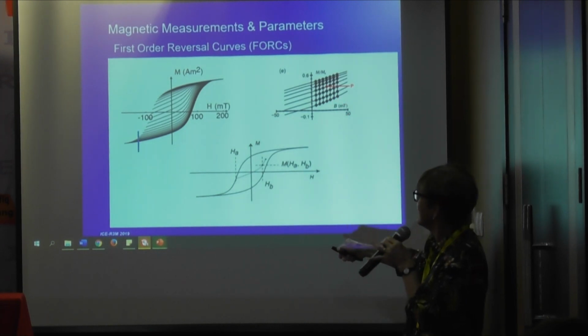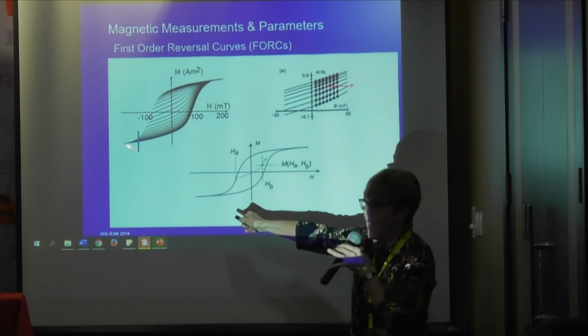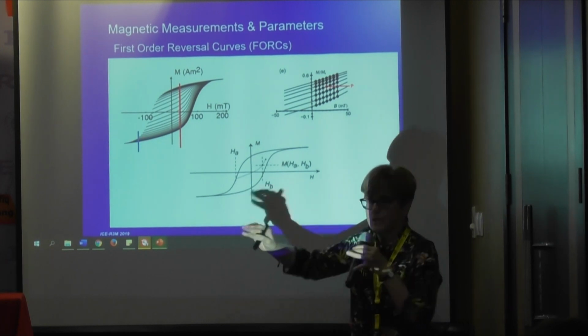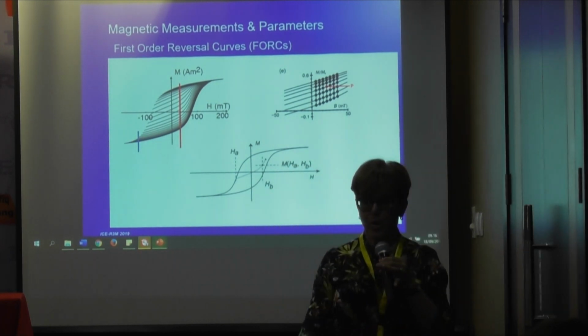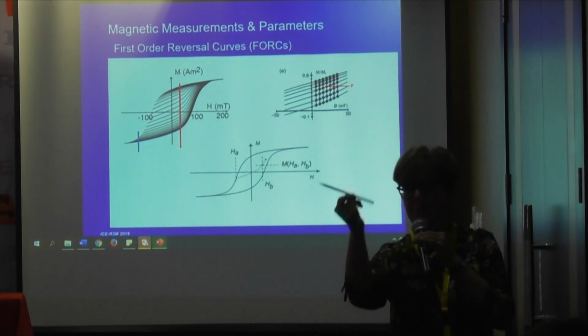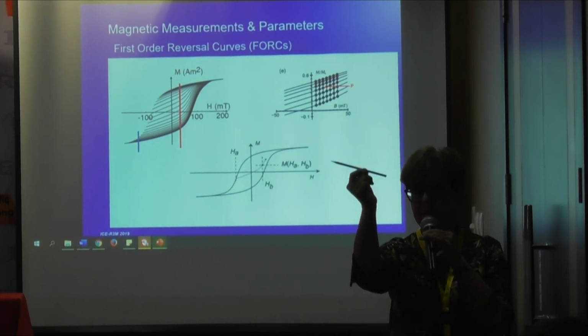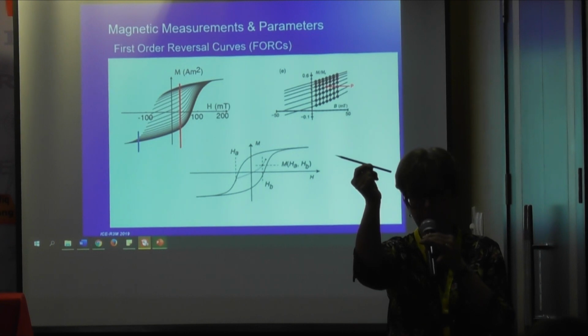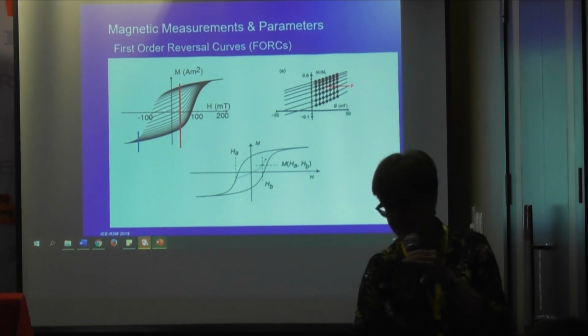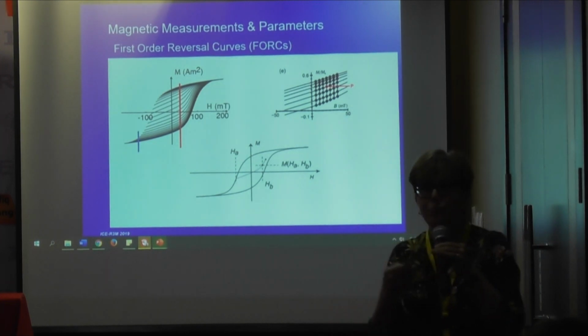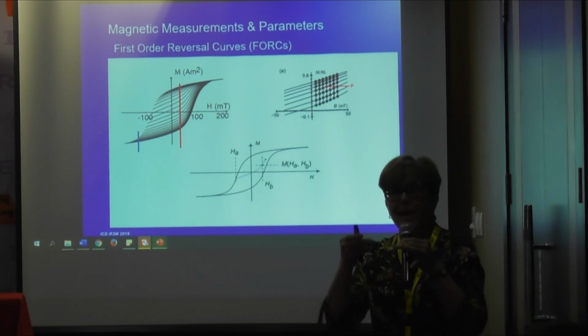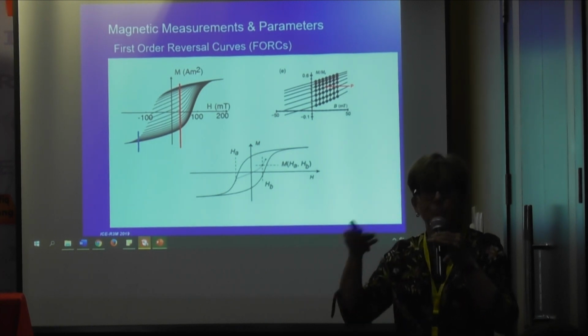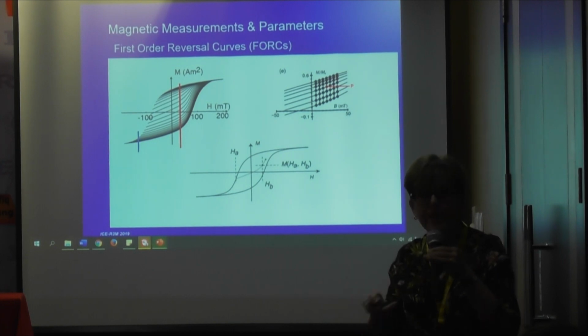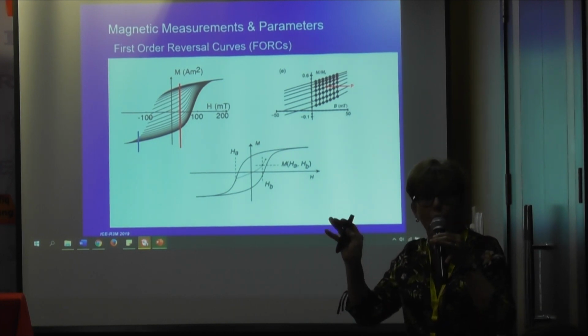Next. If I'm down here, I can see the slope of the line of my hysteresis loop from curve to curve is always the same. So maybe my last curve looks like this, the next to the last looks like this, the next to the last looks like this, but they all have the same slope. So in principle, what this is telling me is my magnetization is saturated, it's reversible. It's not contributing to the hysteresis, to that open loop.